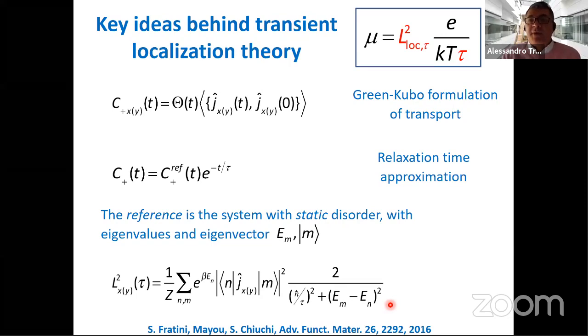But if you think about it, it's the same in band theory. You will not be surprised if you compute the effective mass and you change the sign, you get the same result. So one way of looking at it is that the transport is very coherent. There is no time in 1 picosecond to lose the coherence. Therefore, the charge will interact with itself as it moves, and therefore the sign of the interaction will create negative and positive interference. By the way, this is true for the hole.